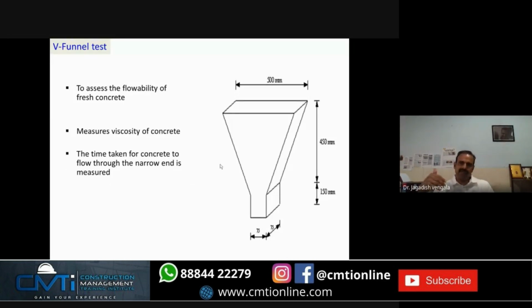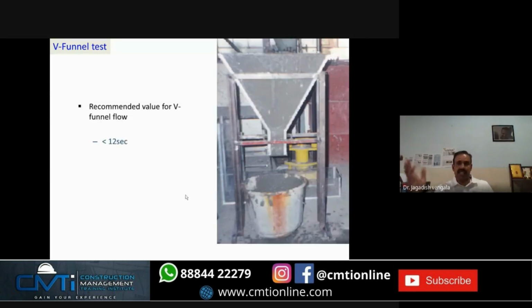Coming to the next test, that is V-funnel test, we assess the flowability of the fresh concrete. I don't know how many of you have properly followed the chemistry. When you check the viscosity of the resin or viscosity of the flow, we flow through a V-funnel and it flows through a small orifice. Time taken to flow through the small orifice, we measure it, which gives you the flowability or viscosity of the resin or whatever. So similar test, this is the V-funnel dimensions. The time taken for concrete to flow through this narrow end, you will measure it. Recommended values are between 8 to 12 seconds.